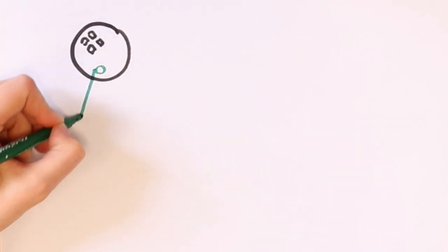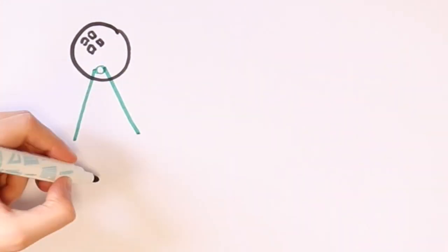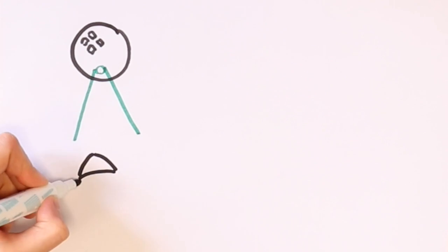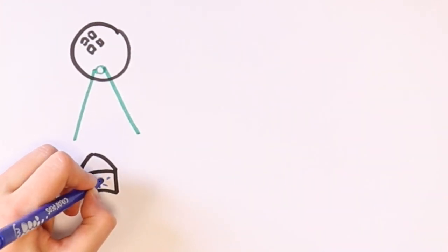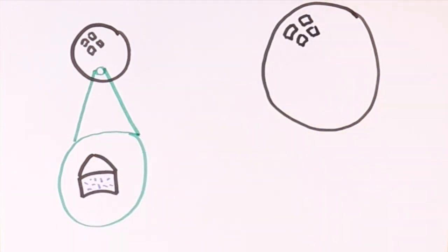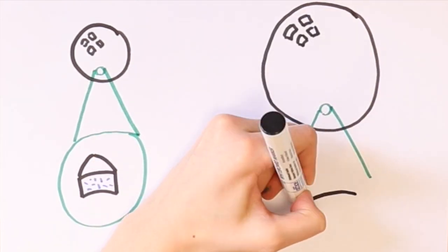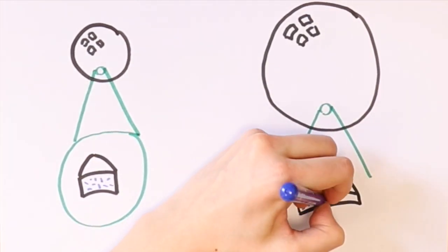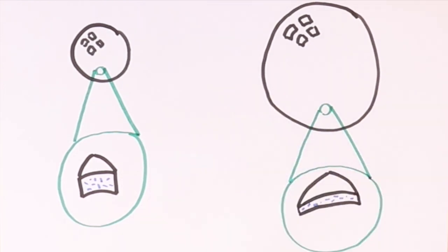So why is this expansion so important? Our liquid crystal balloon, which we call a shell, is actually a rubber, just like the party balloon. Before inflating, the shell is thick and the molecules are disordered. When we inflate it, the rubber has to stretch in all directions in the shell plane, and the molecules then have to orient into that plane. But in that plane, they can point in any direction, just like the spaghettis on the table. This is how we get the negative order parameter.